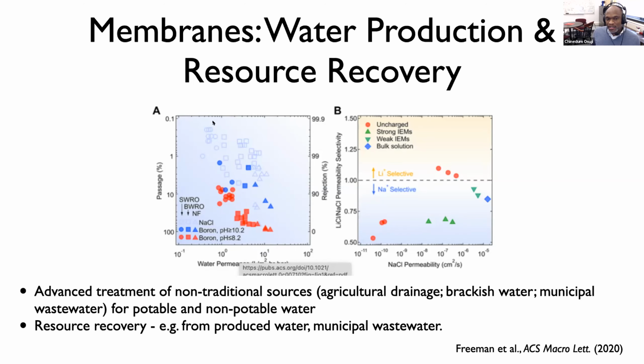And what this plot starts to highlight is a point that will become a central point later on in this discussion, is that we have difficulties in the treatment of wastewater due to the performance of membranes, current state-of-the-art membranes. And this is highlighted in what's often been called the selectivity permeability trade-off. And that shows up here when we're looking at passage. This is now passage with numbers increasing downward, right? So this is passage of contaminants through various types of membranes here, reverse osmosis and nanofiltration membranes, as a function of water permeability. And as the water permeability goes up, the passage of these contaminants also goes up, which sets an intrinsic limit to the rate and purity with which you can purify water.